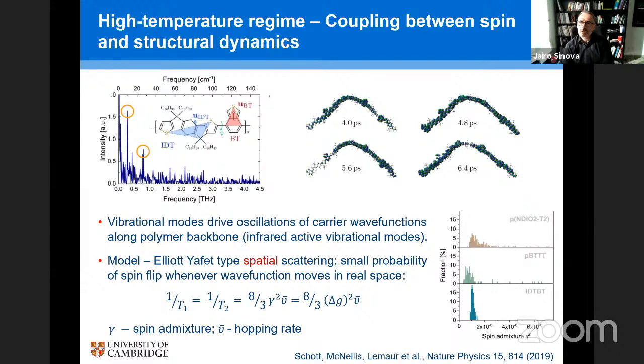But in this, we do have the nice thing that there's some scaling that we observe with the different molecules. And that's the thing that we have tested thoroughly in a couple of works that we reported on. But yeah, it's not very strong, unfortunately. So you don't have manipulation as in the other system.